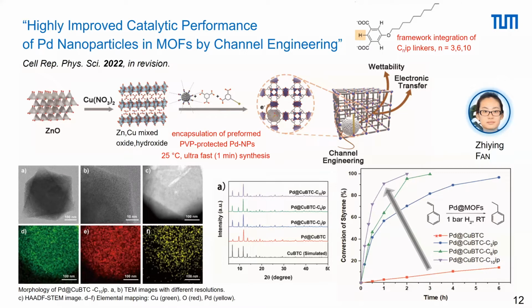So the red trace here is just the unmodified, not defect-engineered MOF host material, which has a very poor catalytic performance. And if you increase the chain length of your defect linker, then you increase the wetting, you increase the hydrophobicity of your host matrix, and this boosts the catalytic activity very much. So, in 2 hours to 100%. So this is one example of fine-tuning a nanoparticle-based catalyst system by integration into a defect-engineered, tailored MOF system.